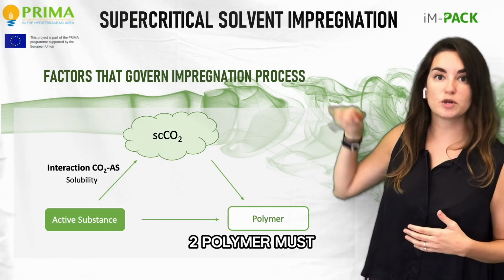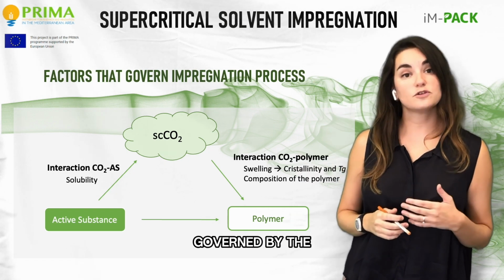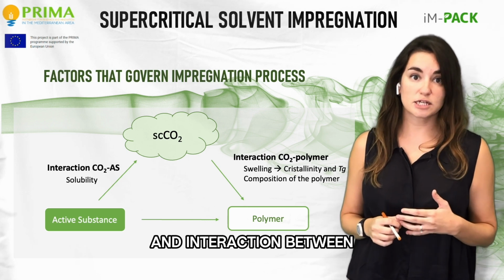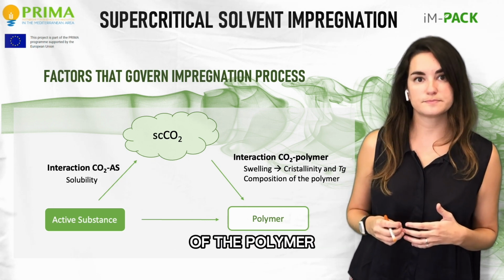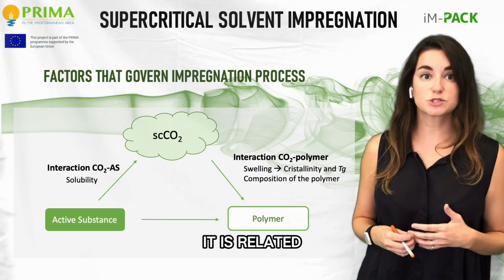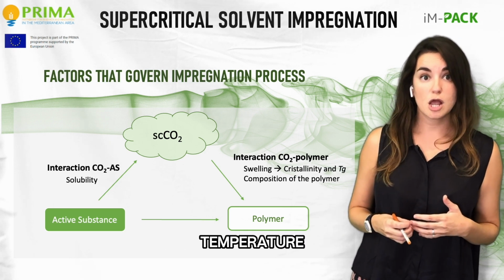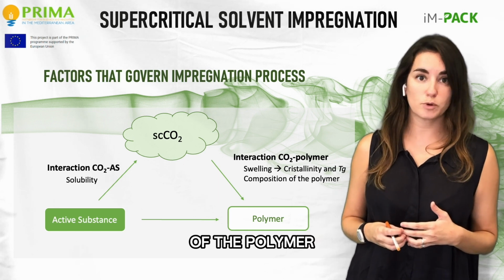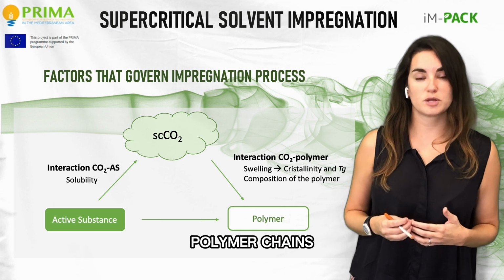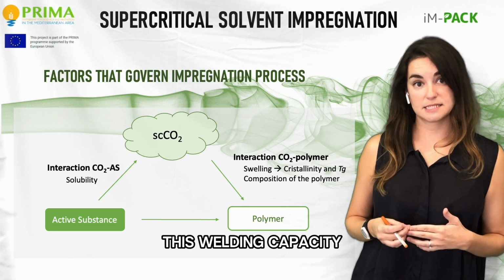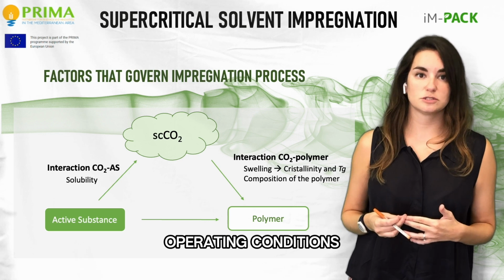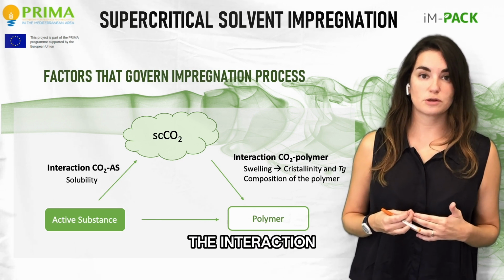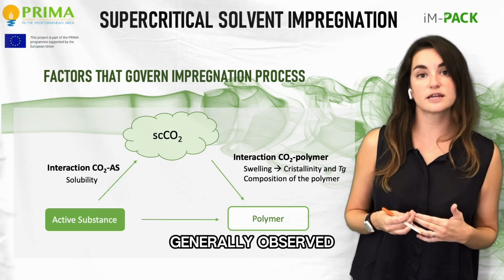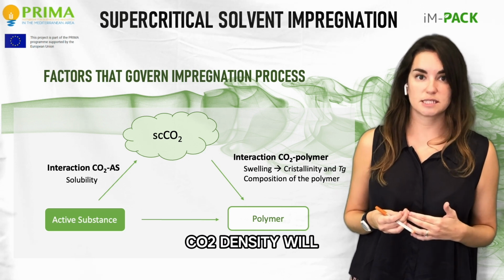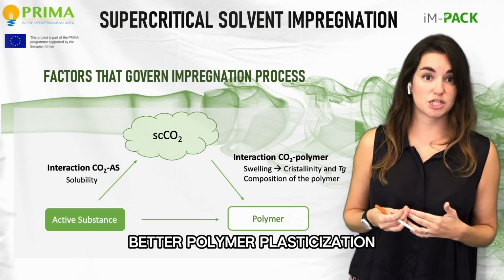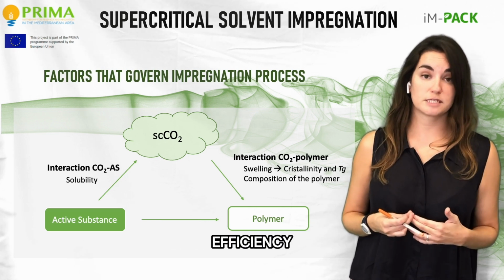Second, the interaction CO2 polymer must be favorable as well. This factor is governed by the swelling capacity of the polymer and the interaction between CO2 and the functional groups of the polymer. Regarding swelling capacity, it is related to the crystallinity and glass transition temperature, which is associated to changes in the amorphous region of the polymer, which determine the mobility of the polymer chains. This swelling capacity can be also enhanced at certain operating conditions. Several studies have focused on the interaction between CO2 and different polymers, and it is generally observed that a higher CO2 density will favor the solid loading due to a better polymer plasticization and to the increase of the internal diffusion coefficients.